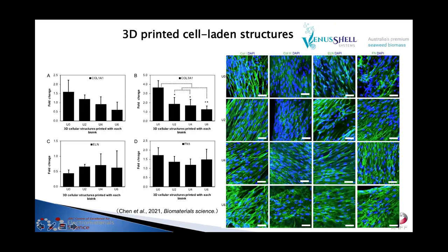Since there was significant cell proliferation, we then looked into the expression and production of the major extracellular matrix proteins. This is gene expression analysis by real-time PCR, and it shows that the inclusion of OMA in the bioink did not induce significant change in the expression of collagen 1, elastin, and fibronectin, but a significant downregulation effect on the collagen 3 gene was noted for structures printed with U2, U4, or U6 in comparison with those printed with U0. The deposition of these extracellular matrix proteins was confirmed following 2 weeks in vitro culture, indicating the potential of our printed cell-laden structures to develop and establish dermal-like properties.